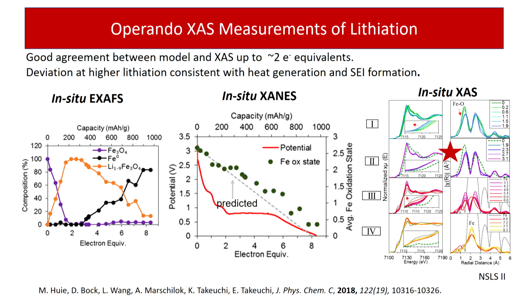And we know that if the Faradaic reaction, meaning reduction of the iron centers, is what's happening, then we can predict the average oxidation state of the iron. Every electron transferred should lead to reduction of 1 iron center. And up to about 2 electrons, we get excellent agreement. If you look at the middle chart, the dashed line shows the predicted value, and the dots are our measured values. But at about 2 electrons, we get deviation, where the iron oxidation state stops changing.